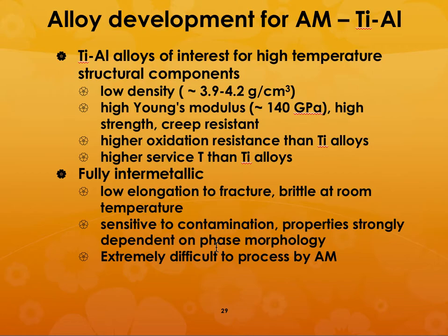It is, but the difficulty is that it is fully intermetallic, which means it has very low elongation to fracture. It is brittle at room temperature. It is sensitive to contamination, and the properties are strongly dependent on phase morphology. It is extremely difficult to process by additive manufacturing.